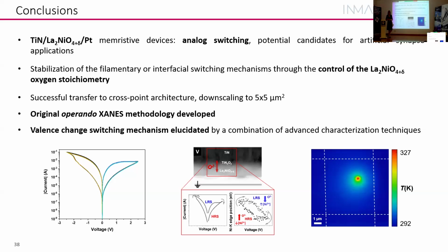It's more a solid solution. So it's not really... No, it's not. Okay, that's a cartoon. Yeah. But it's really a gradient in the oxygen concentration. So for sure, we've measured at the interface that it's not pure titanium nitride. There's some oxygen, but there's no two-phase separation. Do you know how high can be the oxygen to nitrogen ratio?